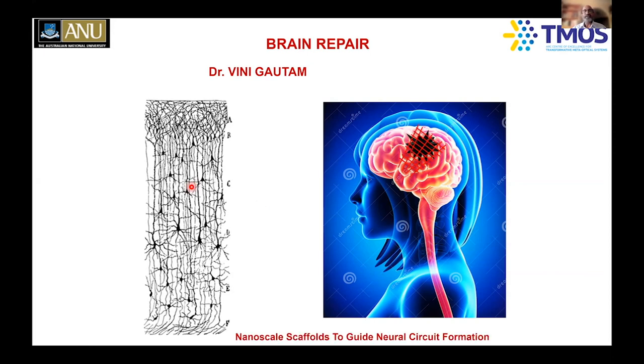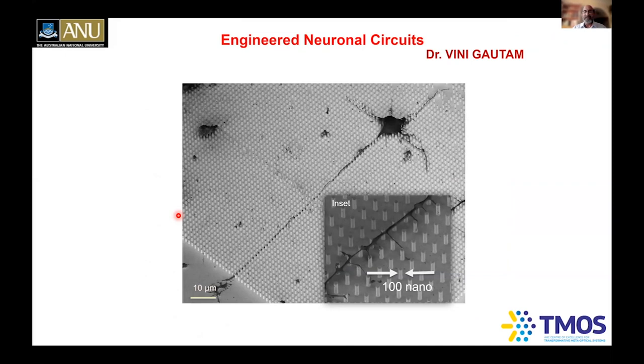And so really, Vini has spent a lot of time optimizing various protocols in order to grow these neuronal cells. So here is an indium phosphide nanowire structure, for example. And then she has grown these rat neuronal cells here. The cell body soma is here. And then these neurites, particularly axons, really follow these patterns beautifully here. And you can see some of the dendrites also following these patterns very nicely. So essentially, these nanowires act like a topographic guide for these neurites to follow particular patterns, for example. Instead of using a single neuronal cell, if you use multiple neuronal cells, what will happen?